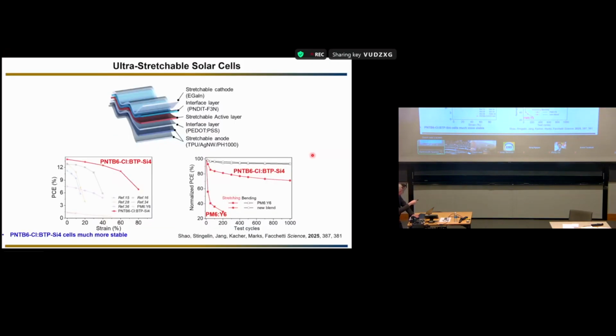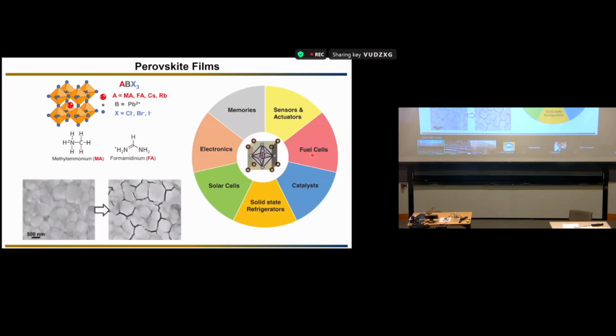And so we made cells, and as expected, the one based on the new blend, you can stretch it. It retains the performance much more compared to the comparison. That's somehow expected. Another thing: I'm not an expert in perovskite at all, but I think I published 5 papers, and I have to thank all the collaborators. These materials, as you know, have wide applicability. One of the problems with perovskite films is that they are very, very brittle. You have a lot of grain boundaries, and that is where the failing mechanism occurs. They are organic-inorganic, more hybrid, depending on which kind of ions you are using. If you want to make this material more ductile, how can we do that?